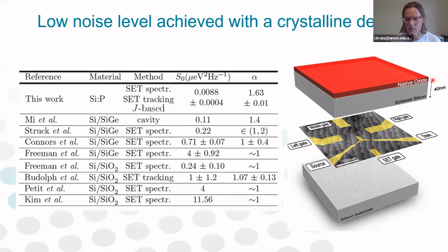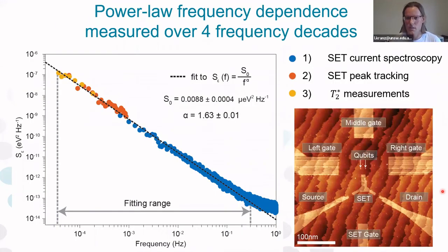The other interesting thing that we notice is that we used SET measurements for the first methods, and then we used qubits for the third method. And yet we see that the spectrum follows the same frequency dependence. This suggests that the noise dominating on the SET is similar to the noise on the qubits, perhaps coming from the same ensemble of two-level fluctuators.